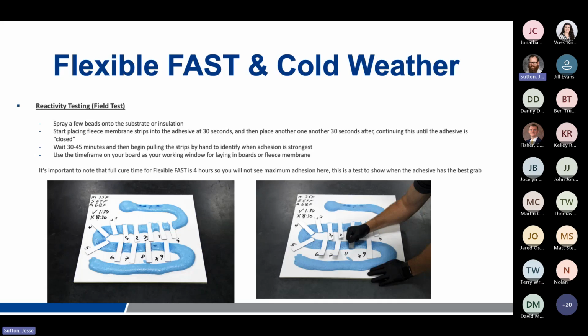So you'll see, if you can see it on the screen there, that check mark is at about 1:30, and then the X is about 8 minutes and 30 seconds. Those are what we would call open and close of our string time. So you can see the material temperature is 75, the substrate 69, and the ambient temperature is 68. So that's ideal indoor conditions. Those numbers vastly change depending on your substrate temperature, your material temperature, and your ambient. So like I said earlier, if you have 40-degree material, 30-degree deck, that check mark is going to move from 1:30 probably all the way up to 8, maybe even 10 minutes. And if you have warm material on that cold, it's going to be somewhere in the middle. So you might get string time in around 2.5 minutes.